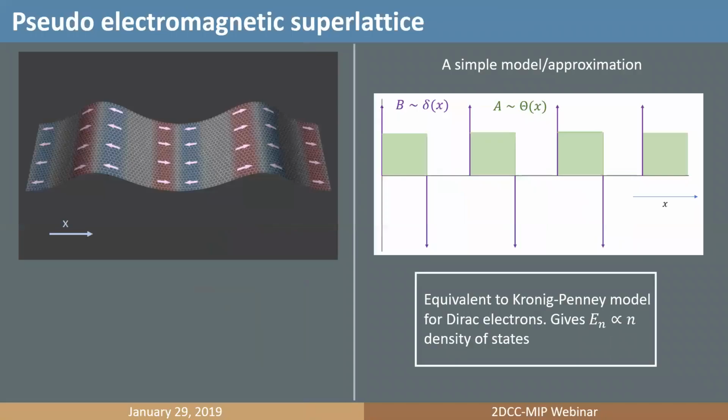So what is really happening here? What is happening is these small regions create their own magnetic field. And these magnetic fields create their own Landau levels, which are going around. Now, since the de Broglie wavelength of the electrons in a semi-classical theory is sufficiently large if we calculate it, the electrons interact with all these Landau levels. So all these Landau levels interact with each other. And out of that comes E proportional to n.